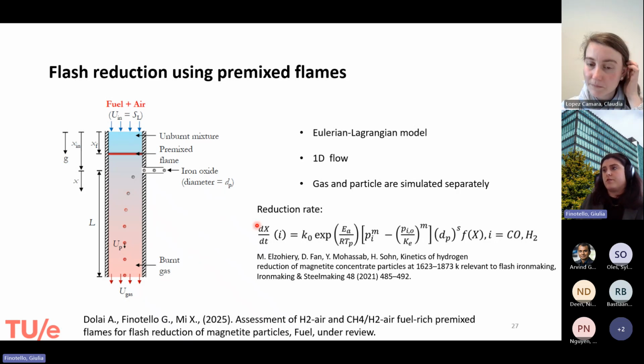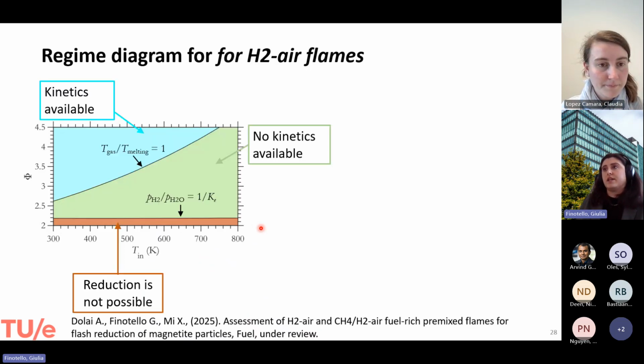And what we did first was to define a regime map for this hydrogen-air flame. So you can see the equivalence ratio and the inlet temperature here. If we are below, in this orange region, reduction is not possible because the partial pressure of water vapor would be too large. And then, again, for equilibrium, we will shift the reaction to the opposite side from what we want.